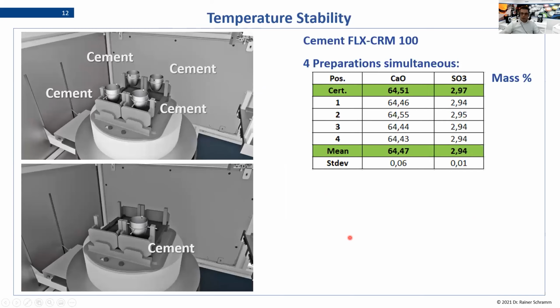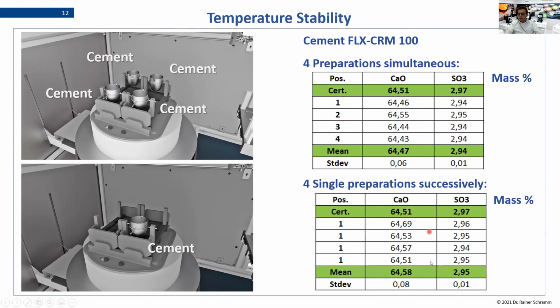But let's see now how the temperature stability is influencing our analysis. So let us assume we have 4 cements and we fuse them. And of course, when all that I told you is true, then you will see for all 4, for the main component calcium, a fantastic standard deviation, a very high precision. But also for the volatile element like sulfur, you will see the same. But the question we had is, what happens if, for example, you place only 1 crucible in the system and you repeat this 4 times? So like you see here, there's not a real difference. So you even could use only 1 or 2 or 3, and whatever place you choose, because of the turnaround it's always the same conditions on every position. So in this way, it is guaranteed that the system is as flexible as possible.